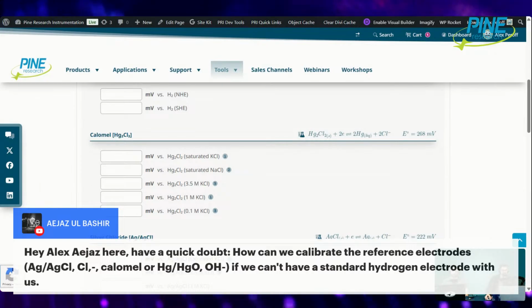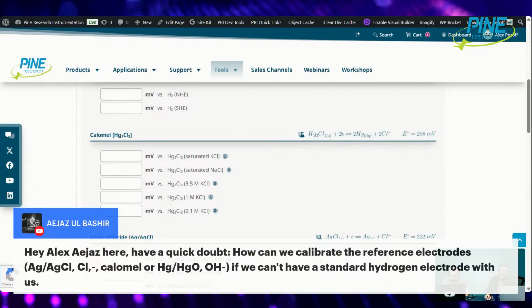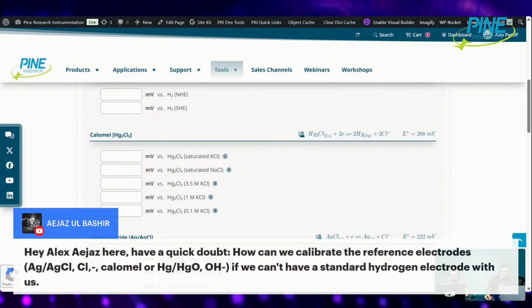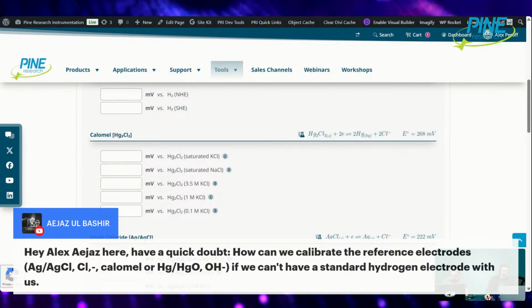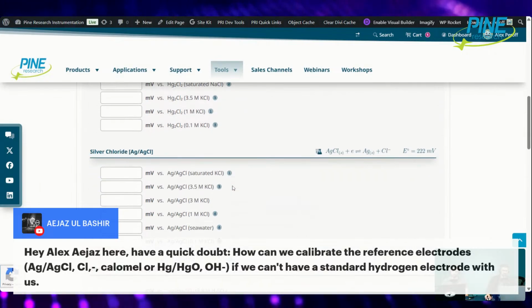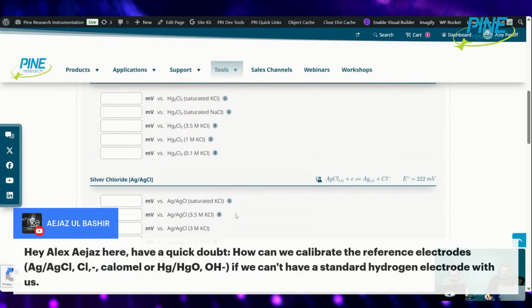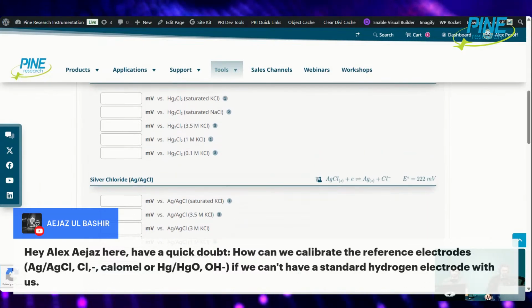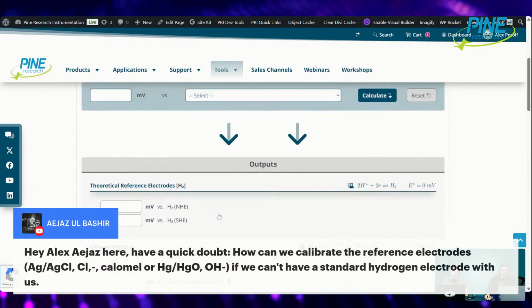If you're off, if you're getting something like 35 or 30, you're like 15 millivolts off. One thing you want to make sure of is to double check the chloride ion concentration in both of these. They should ideally be the same chloride ion concentration. They should be saturated. That should be the easiest way to do it. As you can see, you can have many different chloride ion concentrations for calomel, and also for silver chloride. As long as those things are the same, you'll be able to tell what the difference is.